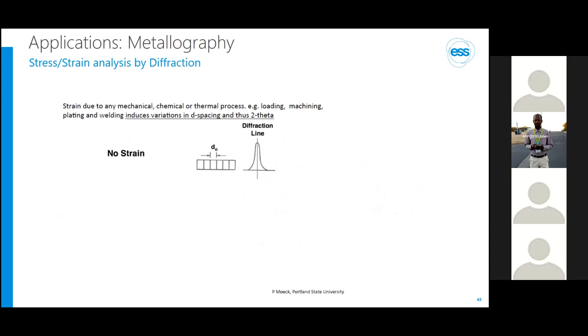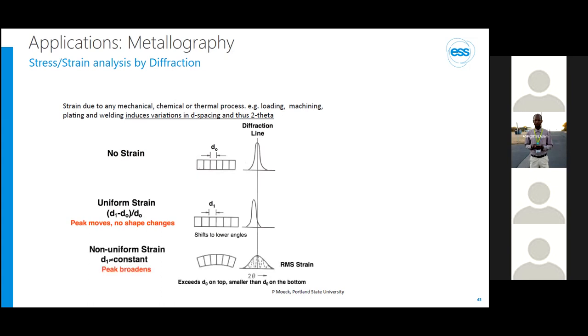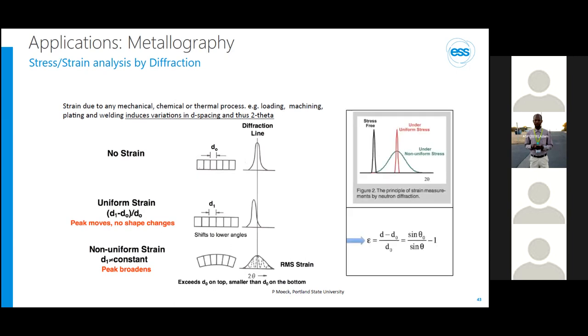Since we measure the position of these Bragg peaks with a high accuracy, we can use them to quantify internal strain and stress inside of materials. And if there's a uniform strain, the Bragg peak will simply move. And if there's non-uniform strain, then we also have additional peak broadening. The lattice spacings inside the material then act as internal strain gauges, and one can simply infer residual strain or applied strain from comparing the measured d-spacing with the reference d-spacing in the unstressed state, called d0.